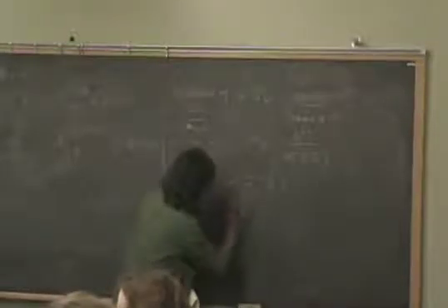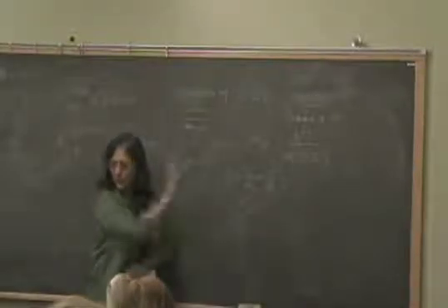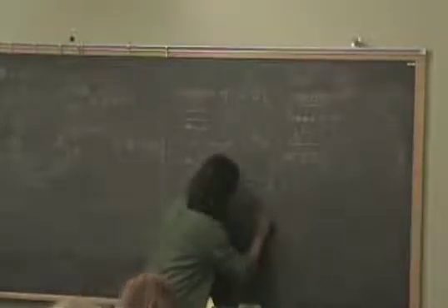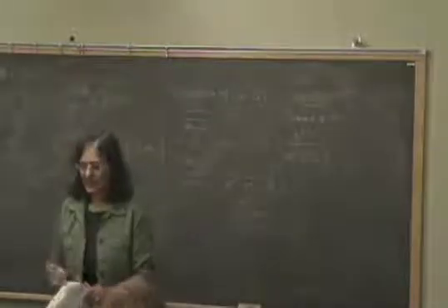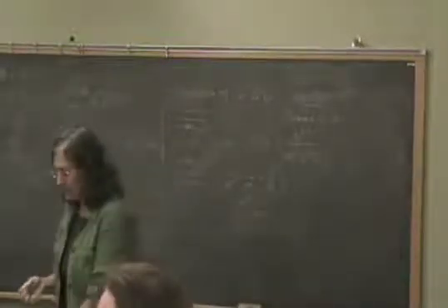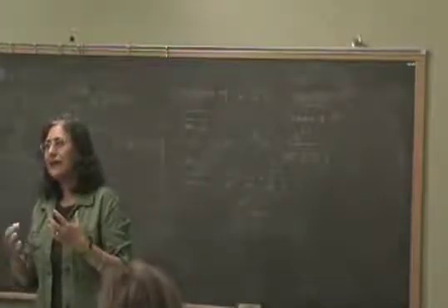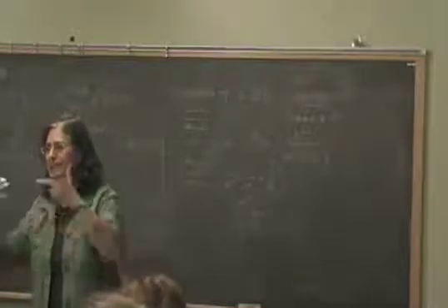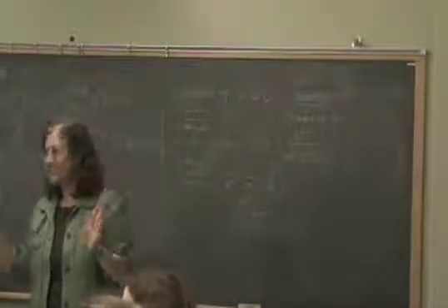Because what I have is, let's say in gallium arsenide I have something like this. So each of these masses, and you have to worry about light hole, heavy hole, we're not even going into that. But basically each of these would be effective band masses. But do we still have that in a quantum dot? Yeah, okay, so that itself is an interesting question. You can still have this mass become a second derivative of your eigenvalue in some basis.